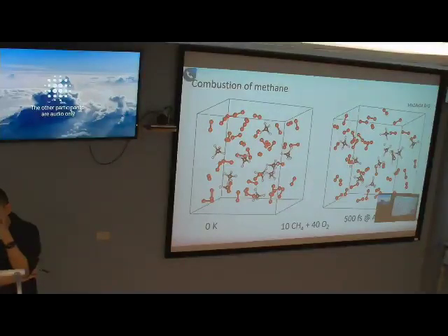So it should be very much dependent on the density, and to the naked eye the distance between atoms looks about twice as large as in the previous ones. So you may compress it like 2 times, maybe not in one step, because in one step it will just explode, but compress, run dynamics, compress, run dynamics a little.